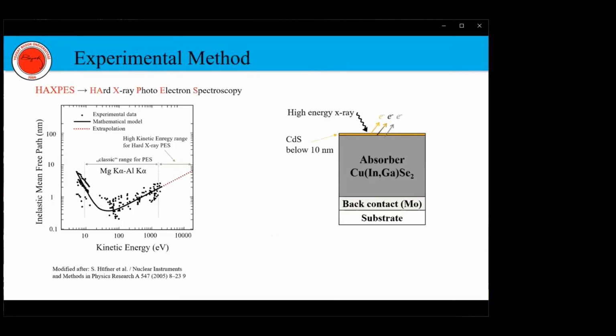The experimental method we used in this work is hard X-ray photoelectron spectroscopy, HAXPES. If we look at the universal curve of the inelastic mean-free path, kinetic energies between 10 and 1000 electron volts correspond to an inelastic mean-free path of about 2 nanometers. These energies can be achieved using standard lab-based X-ray sources like magnesium K-alpha and aluminum K-alpha. If we increase the kinetic energy of the photoelectrons, we can correspondingly increase the inelastic mean-free path up to 10 nanometers. So using high energy X-rays, we can investigate the absorber buffer interface if we have a buffer layer with a thickness of below 10 nanometers.